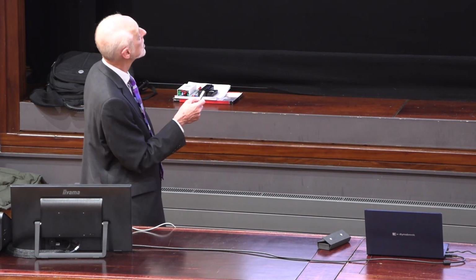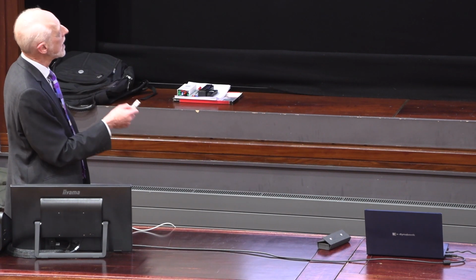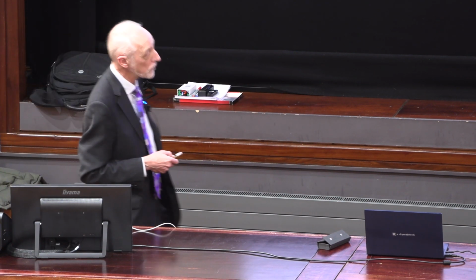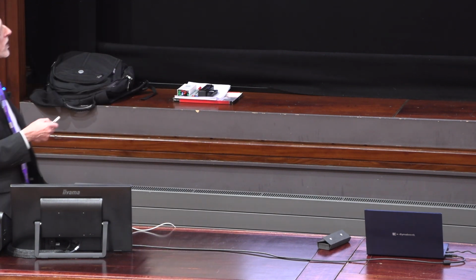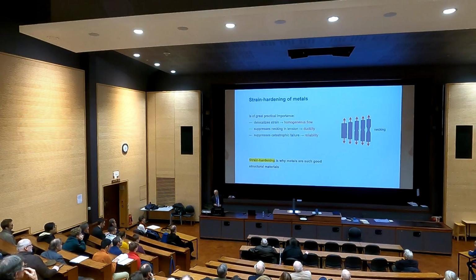So this strain hardening delocalizes the strain, it forces it to spread, gives you homogeneous flow, it suppresses this necking, which gives you the property called ductility, that's that 30%, and of course that all helps to suppress catastrophic failure, and that gives you reliability of your structure. So we could say strain hardening is really why metals are such good structural materials. It's not that they're hard, in fact they can be rather soft, it is that they can harden. It's the hardening that makes them really important.